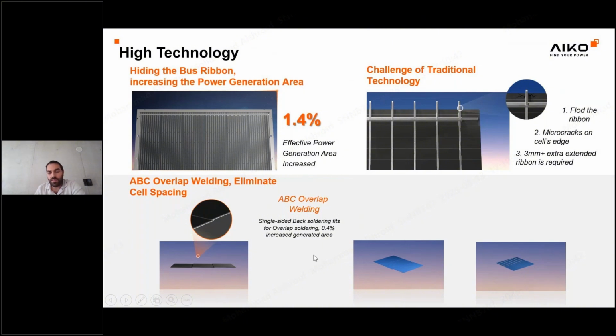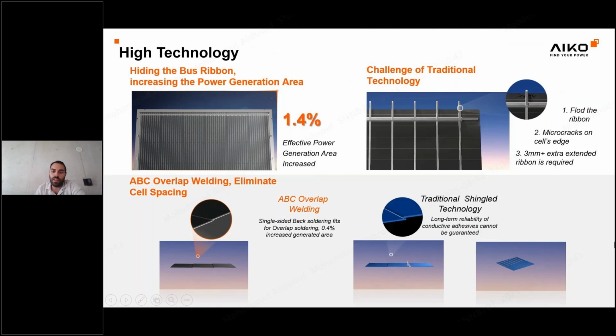We have seen this approach in the industry, firstly in the shingle technology. In the shingle technology, they use conductive adhesive material, but it shows issues in terms of reliability, especially after 3-5 years in terms of the thermal cycle, like summer and winter. The conductivity of these adhesive materials gets less, and the industry has realized a huge drop in the power output of the solar panels.